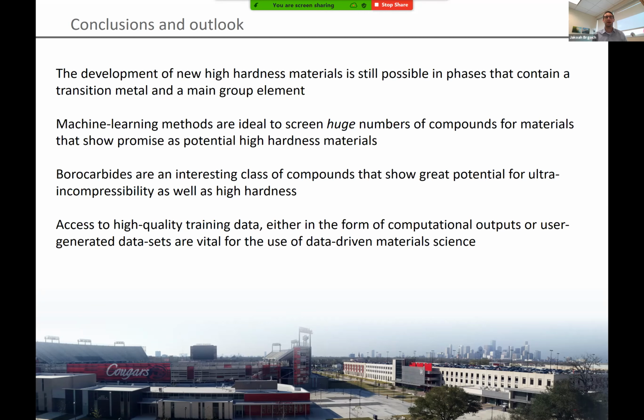Similarly, I see there's some comments about thin films. That's where the advantages of thin films certainly have over bulk materials. Now, my background and strength are in bulk materials, and you have a much harder time doing things like controlling nano precipitation in a bulk material at 3,000 degrees Celsius. Growing thin films is really where the benefit is going to lie. So yeah, I think that's a great question, and if we want to talk about really driving hardness up, that's where the field is sitting, in these sort of hetero structures, if you will.